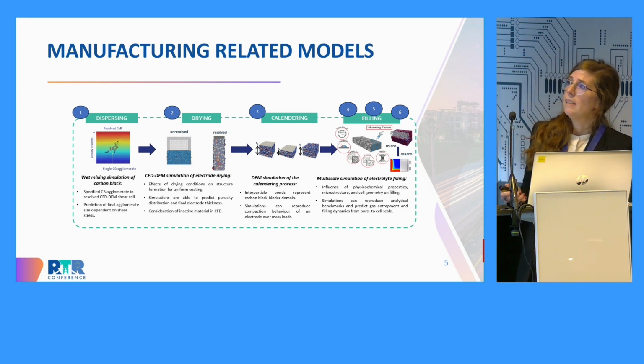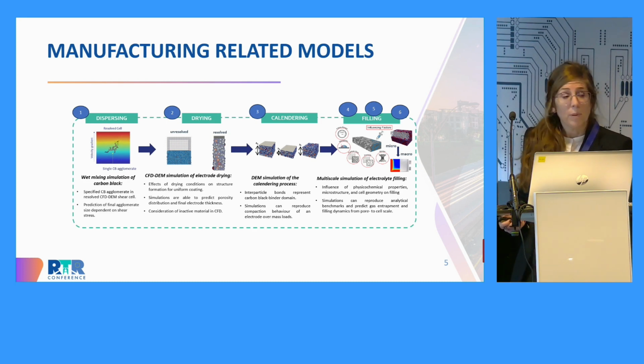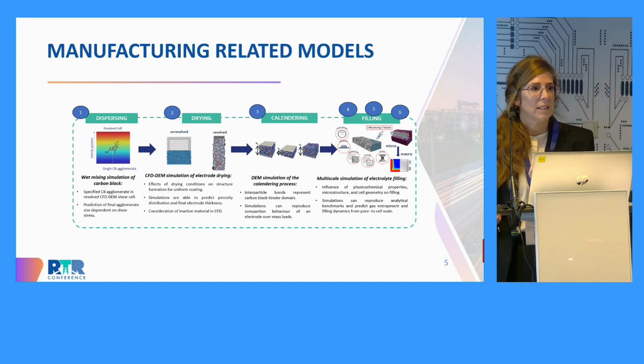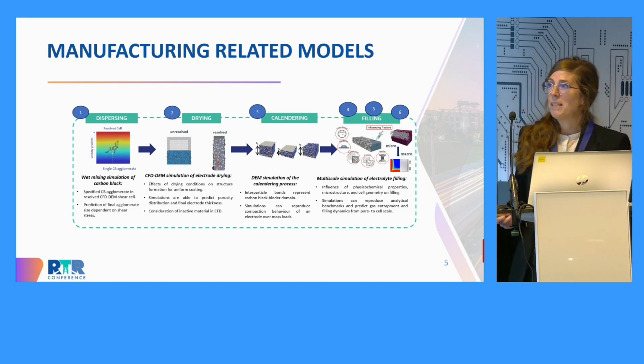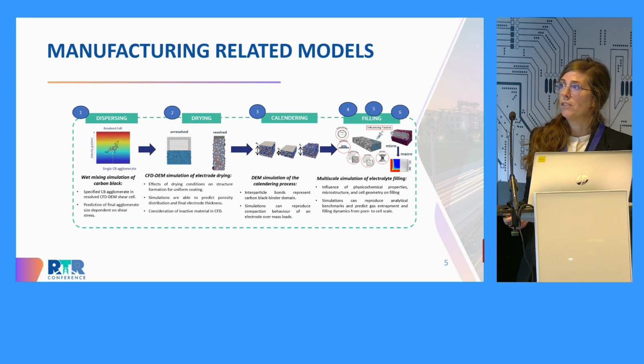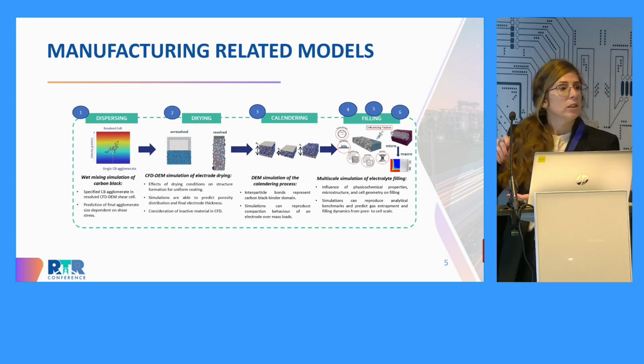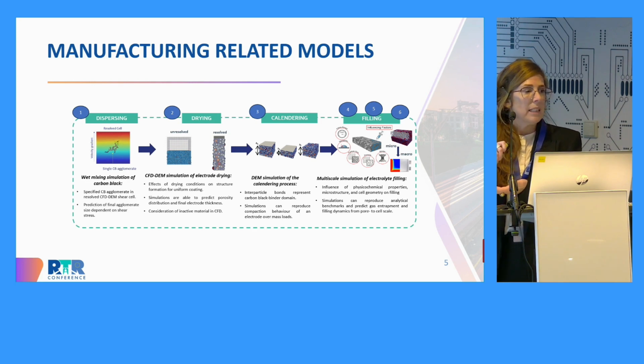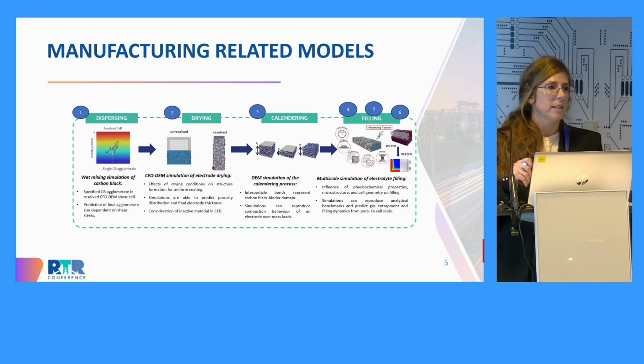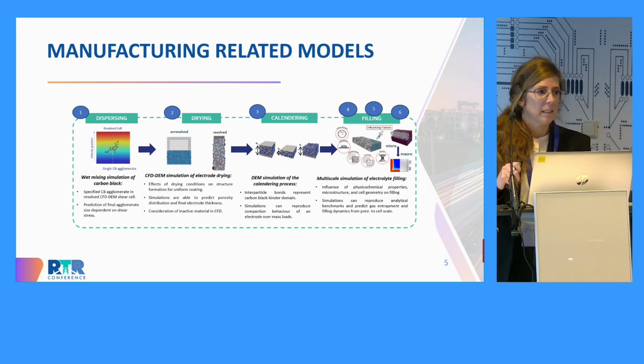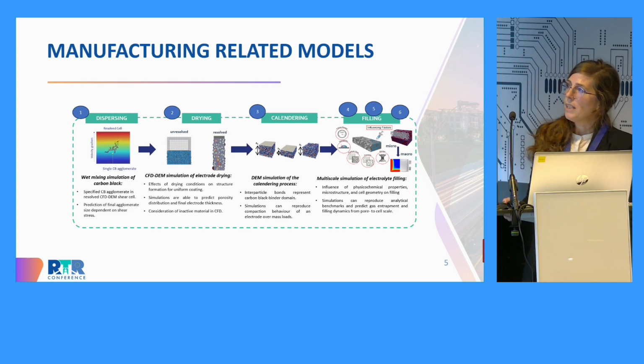carbon black domain. In the drying step, they were able to predict properties so relevant in electrodes, such as the porosity and tortuosity, depending on specific process parameters of the drying. And in the calendaring, again, depending on the pressure that is applied in this specific process, they were able to predict, again, porosity and tortuosity, so that they could also predict ionic resistance, which is very interesting to know in advance in order to see if there will be a certain limitation, for instance, in fast or high C rates. So these are the three models that were developed on the electrode fabrication, and